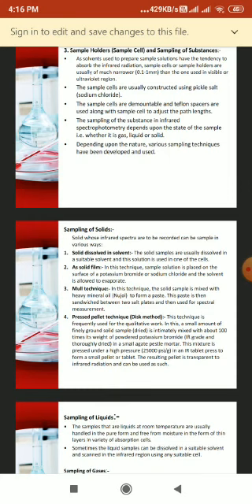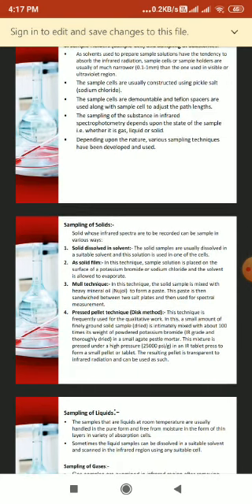Although Nujol is transparent in most parts of the infrared region, it has absorption maxima at 2915, 1462, 1376 and 719 per centimeter. This is the drawback in using Nujol for certain compounds which may have absorption in a region similar to Nujol. This technique is mostly used for qualitative work and not for quantitative estimations.